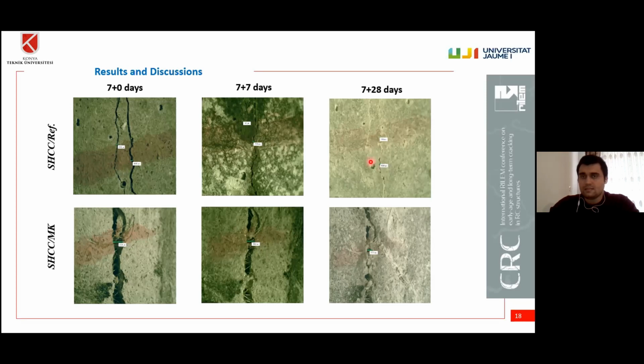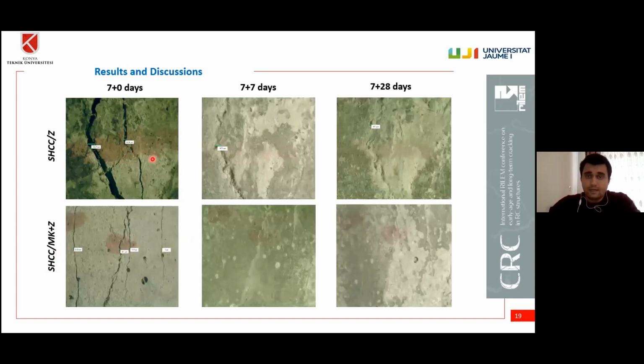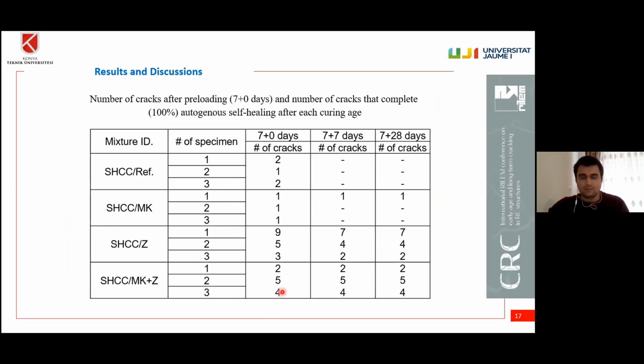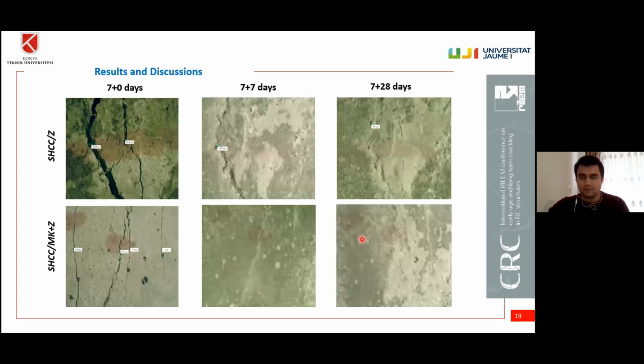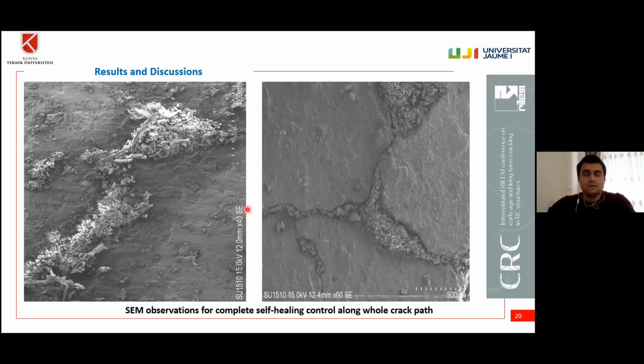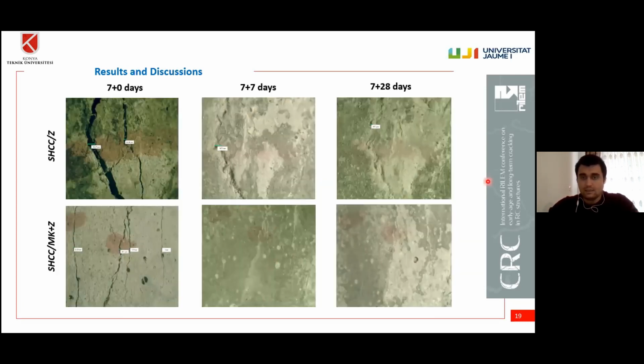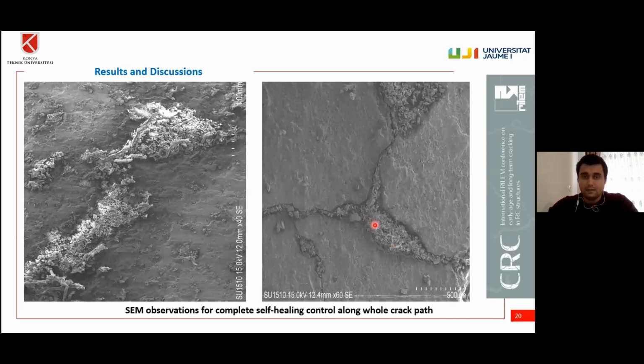We just counted the totally self-healed cracks because we addressed the negative aspect of autogenous self-healing. We just want to see the total self-healing. It was also valid for the metakaolin bearing specimens. And for zeolite, for example here, we had almost total self-healing of cracks. In the binary use of mineral admixtures, these specimens were very responsive to autogenous self-healing, as you can see. For example, this image belongs to the third specimen that has 4 different cracks. You can count the cracks and follow the self-healing process. We made the same observation, so we are sure that we see total, 100% self-healing in the cracks.